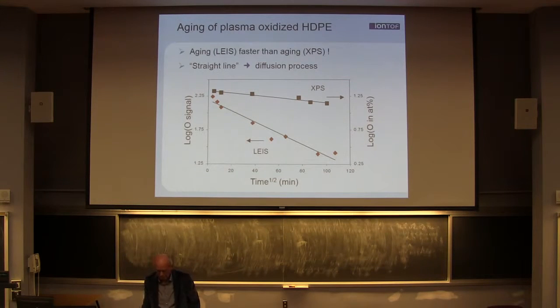And then, well, the background is that many years ago I was responsible at Philips Electronics for the compact disc and everything related. We try to make, you have a polymer and you try to put a metal like aluminum, silver or whatever on it, and you want it should adhere. We try to be clever, so we said, well, let's make many discs, and next week we evaporate the metal on top. It did not stick anymore. After 1 week, everything was gone.